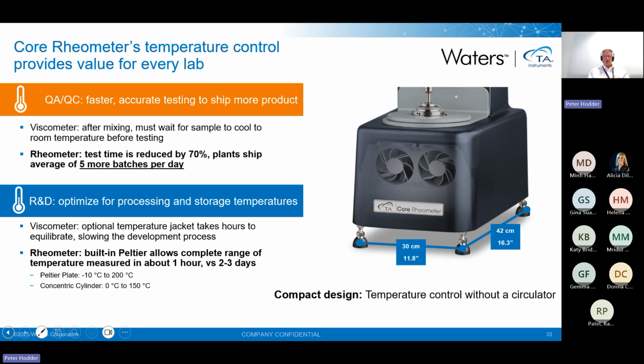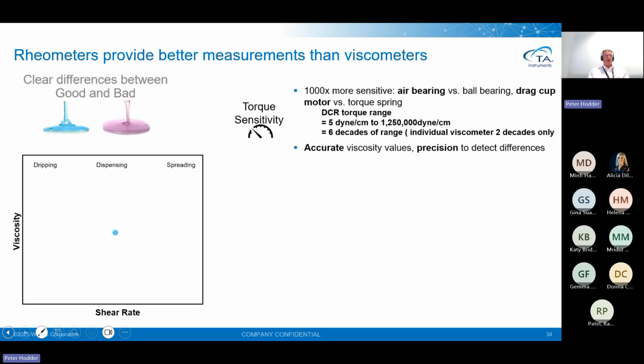I also mentioned that we can measure over a wider range. Well, here we go back to our examples of the pink and good and bad samples. And what we can understand is the torque sensitivity is much greater on a Rheometer than it is on a viscometer. It's about 1,000 times more sensitive. That's because we're using air bearing technology rather than ball bearing. We're actually using a drag cup motor rather than a torque spring, both being calibrated, of course. So the DCR torque range in dynes per centimetre is 6 decades of range, whereas most viscometers struggle to have 2.